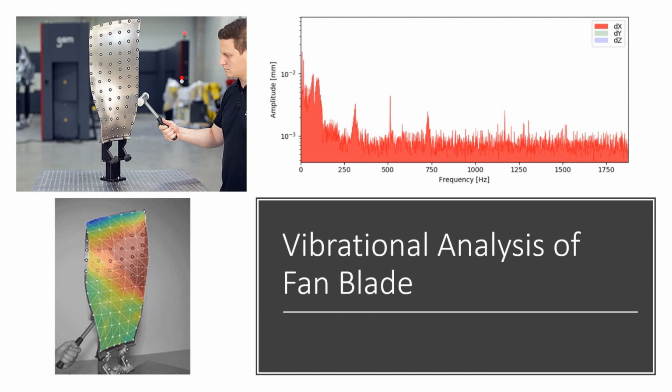The images analyzed the locations of the reference points in the vibration analysis function within the Aramis software, and the operating deflection shapes were determined. The measured operating deflection shape can be compared to the simulated mode shape or the actual shapes from previous measurements. If any difference is measured in the characteristic resonances over life, then there could be a crack somewhere in the blade, and it may not be suitable for flight.